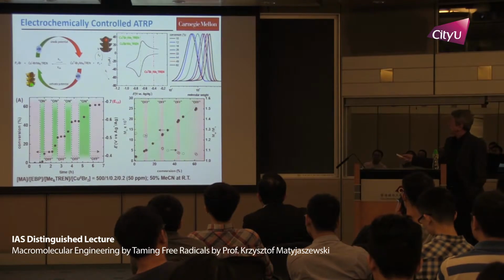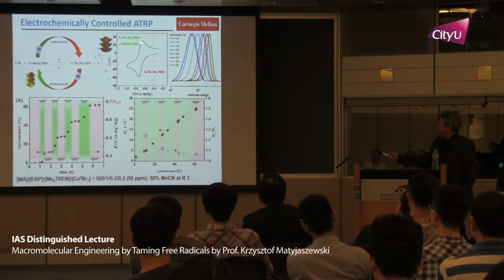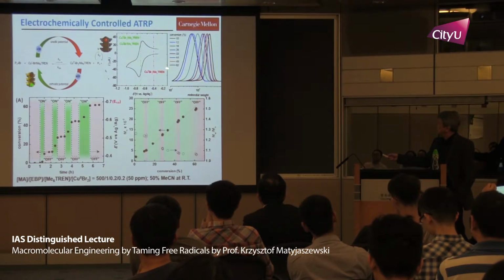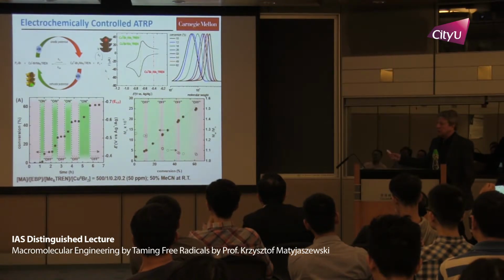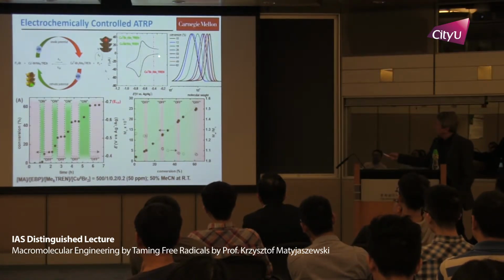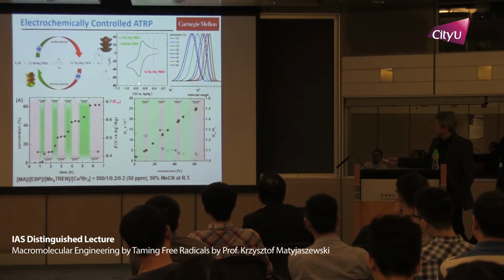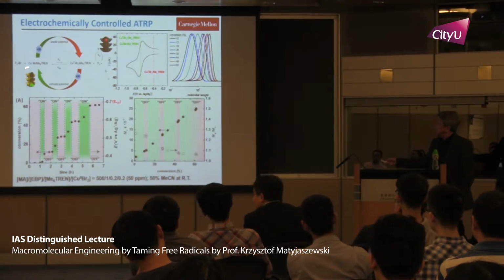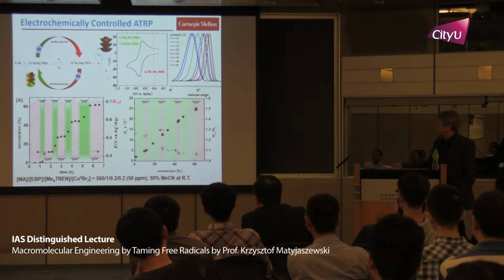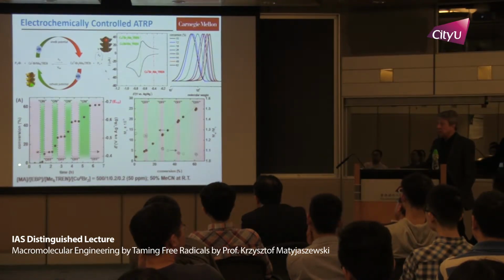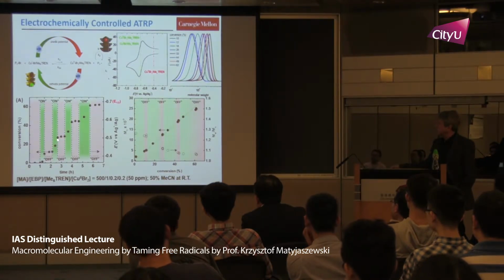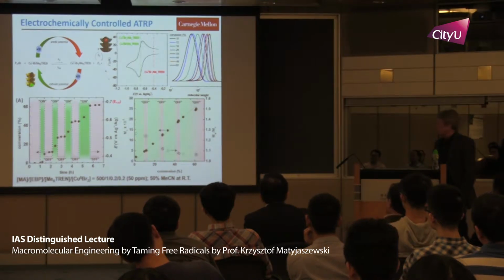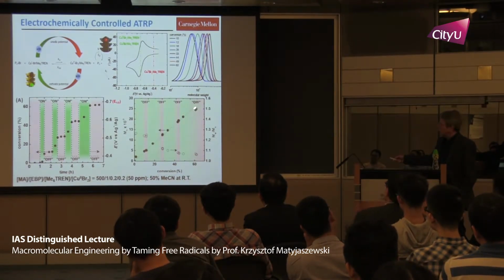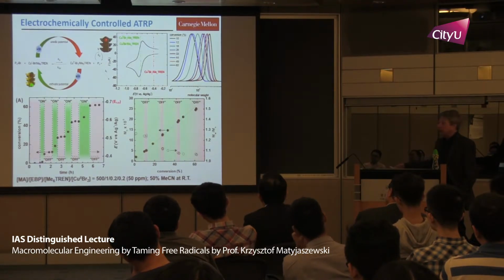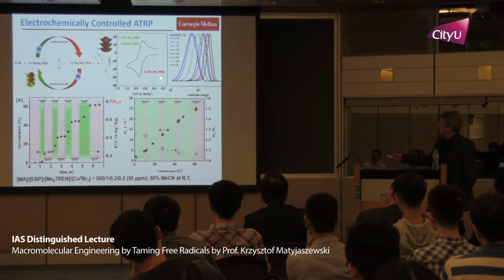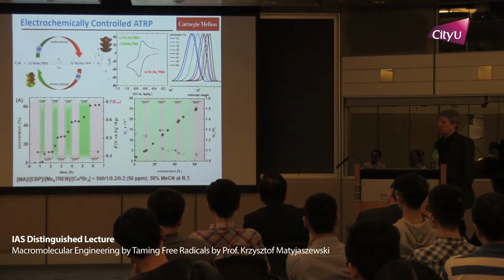So here's an example. If you look at this, one of the most active systems, hexamethylated TREN as a ligand, if you have sufficiently positive potential, there is no current flow, which means there is no reaction. But then, if I go to more and more negative potential, for example, negative 700 millivolts, in that case current flows, then I can start the reaction. And I can flip it on and off between 400 and 700: 400 nothing, 700 it starts, 400 stops, starts. I can climb to whatever conversion I want. And you could see that the molecular weights very nicely increase with conversion, and the dispersities go to values like 1.05 in the best living polymerization. The entire molecular weight distribution moves cleanly to higher molecular weight.